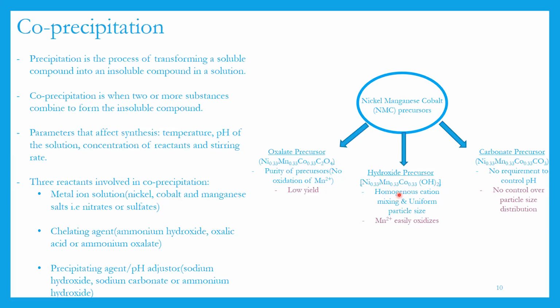With hydroxide, you get homogeneous cation mixing and also uniform particle size from the synthesis. But the drawback is that the manganese easily oxidizes, as I mentioned. And then with the carbonate precursor, you're using carbonate to precipitate out, so you do not have to worry about controlling the pH during synthesis. With the hydroxide precursor, it must be maintained at 11 and above, and the oxalate has to be maintained at a pH of 8. But the drawback is that you have no control over the particle size distribution.